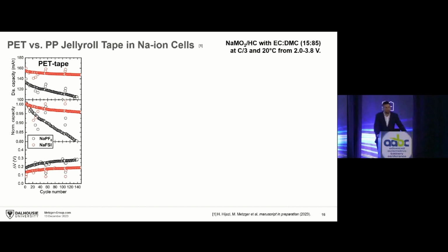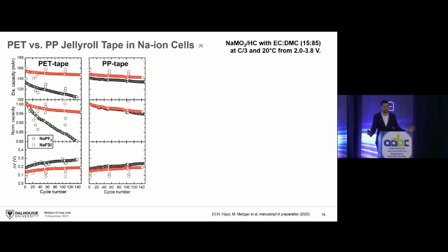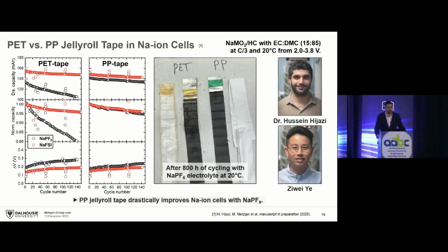So if we use sodium PF6 as a salt in our sodium-ion batteries with just control electrolyte, then we thought, okay, this is a bad choice. The capacity fades very rapidly. So we changed to sodium FSI, which is another conducting salt, and we get quite stable capacity retention over these first 150 cycles or so. But you have to be really careful, because you can easily be fooled by data like that, because if you use PP tape, then in both cases, the capacity retention is very good, right? So the tape also has a big influence on the way sodium-ion batteries are operating.